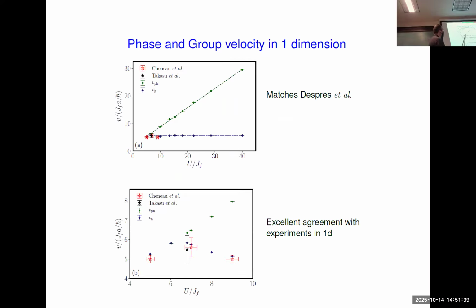And then if we zoom in on this little corner down here, we can compare to experimental measurements of the velocity from Chenon et al. We get a nice agreement with these red points, and then Takasu, they took data in 1D, and we seem to be roughly in agreement with that as well.